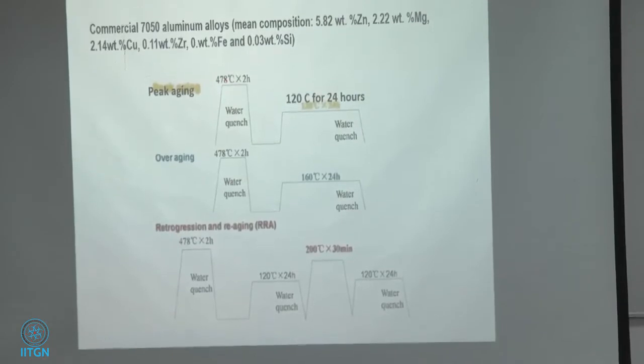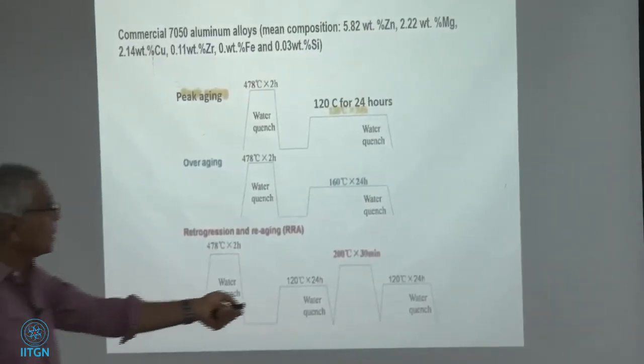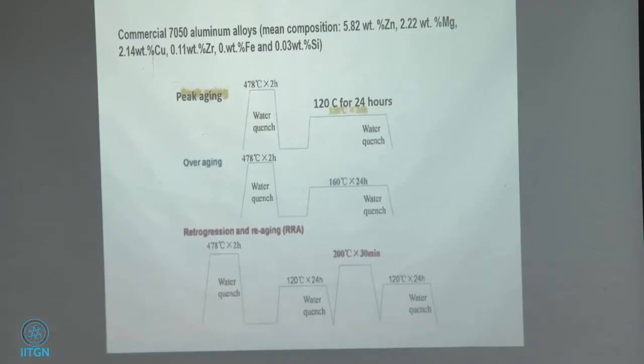So in this case, you already have it here. 478 degrees, that's the solution heat treatment. Solution heat treatment for 2 hours. And then you water quench, just like we said. Then you go for 120 degrees C for 24 hours. So that's your peak-aged water quench, that gives you peak aging. That's your peak age treatment. Your over aging treatment is the same, but 160 degrees for 24 hours, water quench. So if you want to produce a peak age and over aged material, you just follow these two, right?